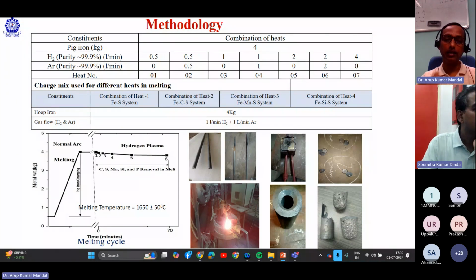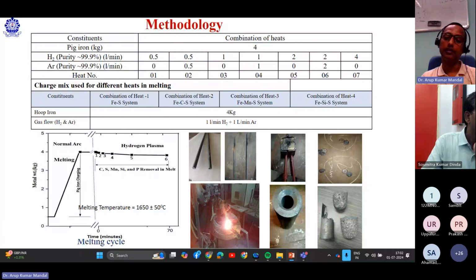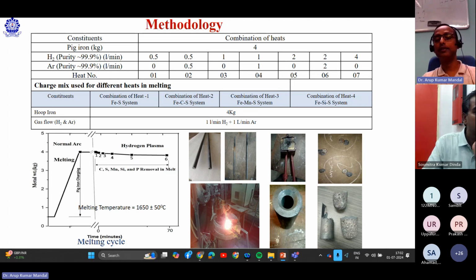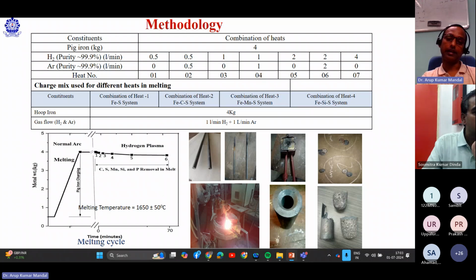And now we are trying to enhance the capacity, because for kinetic study it requires so much liquid metal. Therefore, if we go for the smelting reduction and it generates slag, the capacity will be high. Capacity should be minimum 7 to 8 kg or 10 kg furnace, so that we can produce 4 to 5 kg liquid metal, and the remaining portion we can keep as the freeboard area for handling the slag, the viscous slag.